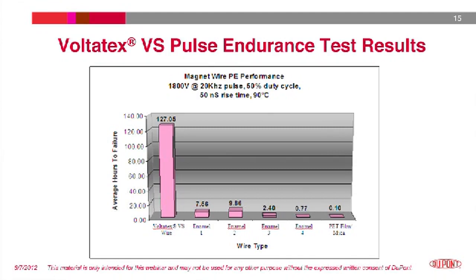We conducted testing on a variety of corona-resistant magnet wire insulation solutions, and the best material was the Voltatex VS wire enamel. Voltatex VS provides corona protection by using nanotechnology at a polymer level, rather than through the use of fillers. We additionally evaluated these insulation materials under AC sinusoidal voltages above the corona inception level, and the Voltatex VS again outperformed other wire insulation under the conditions of test.